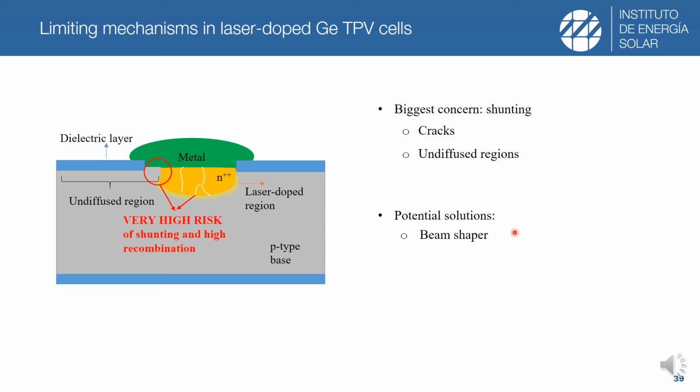And this beam shaper also increases the diameter size, which means that it reduces the energy fluence that the sample receives for the same laser power. Also, the use of this beam shaper could be good because, since the energy profile would be cut, it will reduce the laser power of the system a bit more, and we are already using the lowest laser conditions that the system enables.